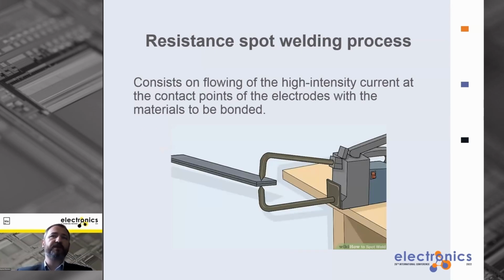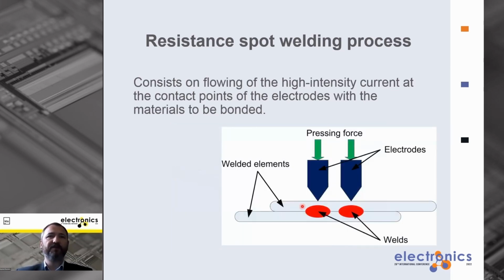The resistance spot welding process consists of flowing of the high intensity current at the contact points of the electrodes with the materials to be bonded. The materials are heated to the melting points, and if they are pressed with an appropriate force, the weld is formed thanks to the solidification of the melted materials. And in the industry, we would rather find the spot welder constructions like shown in this figure. But for the cell welding, we use this kind of configuration. So the electrodes are next to each other, which in fact gives us two welds.